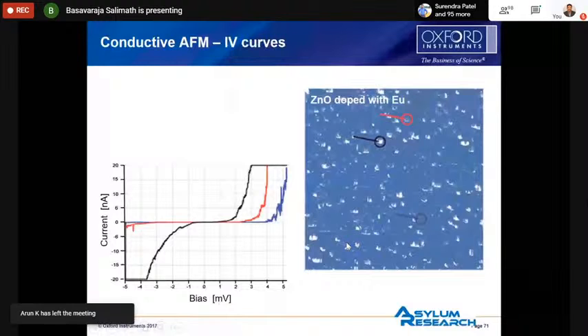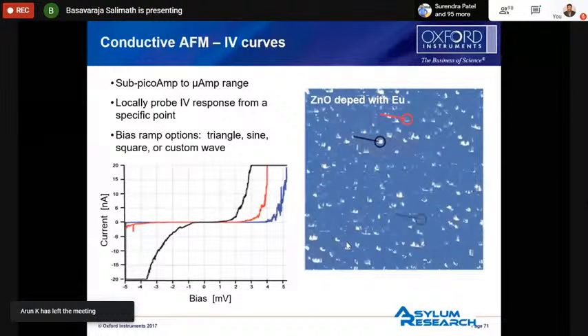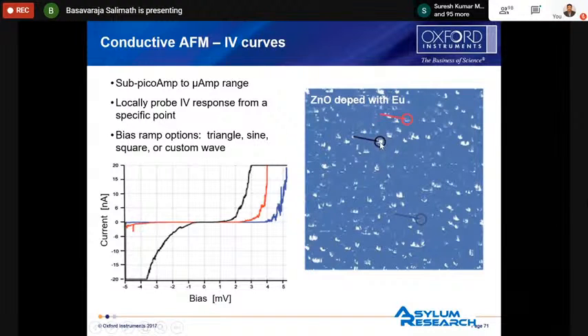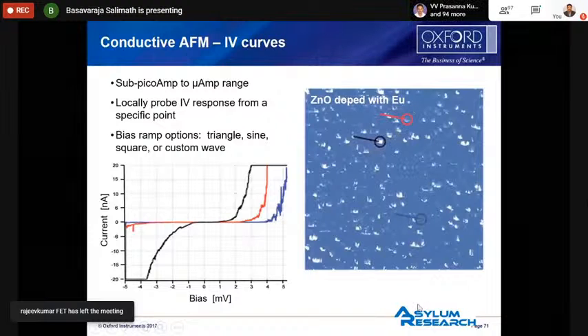And also we can do IV curves. This is some ZnO doped with Eu. If you want to do an IV curve exactly on this spot, you can do it. You can see three different IV curves at these spots we did. So like this, we can measure the conductivity properties on these particles, nanoparticles and all.